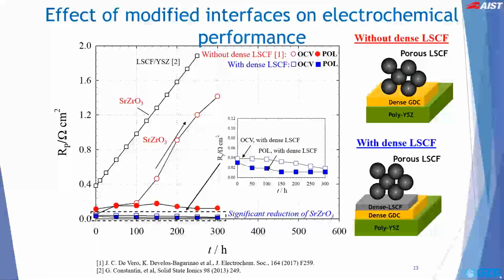For this experiment, we utilized a polycrystalline YSZ substrate upon which a dense GDC interlayer was prepared using PLD. In addition, a dense LSCF layer of approximately 300 nanometers was subsequently deposited. Porous LSCF was then screen printed and co-fired at 1080 degrees Celsius. The electrochemical tests were carried out at 800 degrees Celsius up to a total of 300 hours in both open circuit voltage and polarization. The slide shows the comparison of the polarization resistance for the two types of samples.